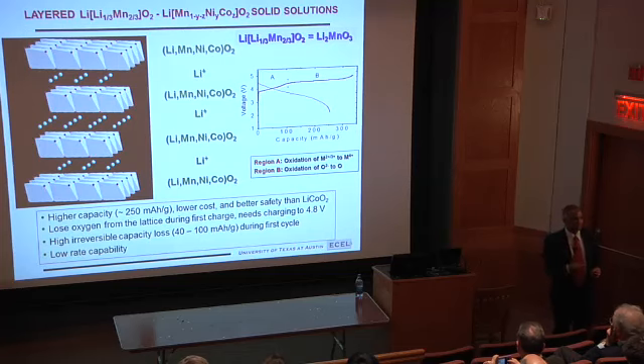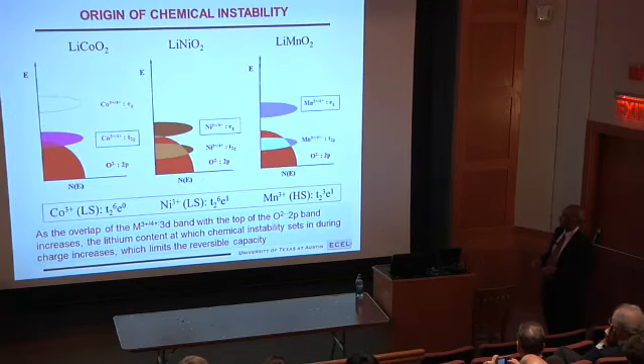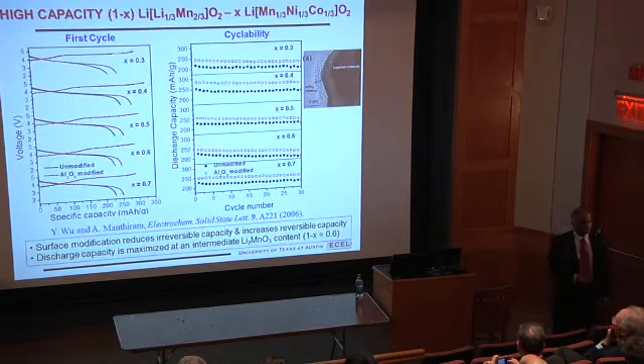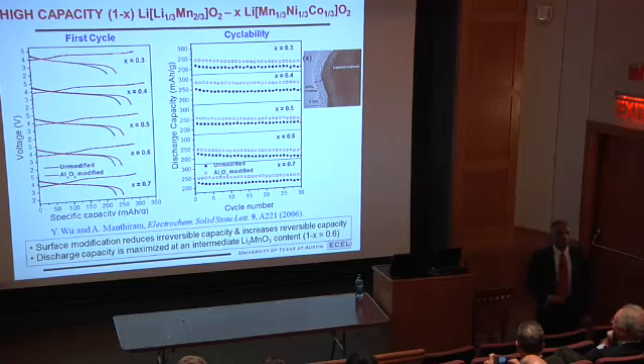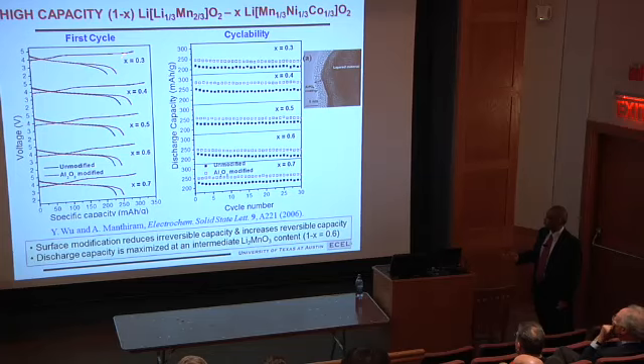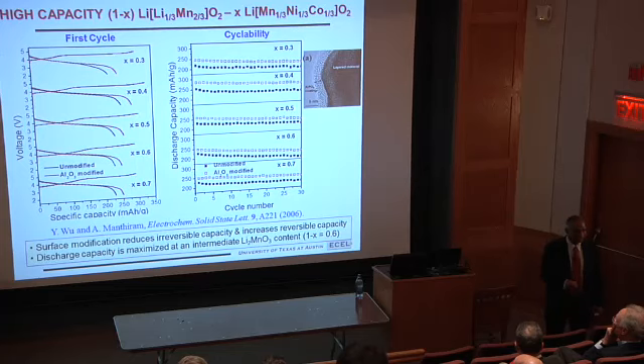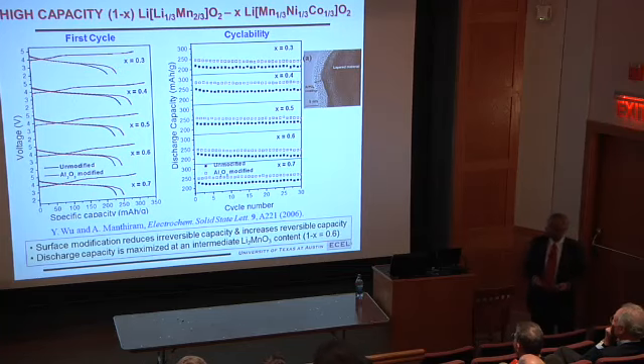It cannot be charged and discharged fast. So we have done some work. What we did is make the material, then chemically coat with aluminum oxide or aluminum phosphate. When you do that, you see the red ones are after coating, the black ones are before coating. The difference is decreased between charge and discharge. So that means we decrease the irreversible capacity loss in the first cycle, and that helps to have higher discharge capacity, as you see here. Red ones are after coating, the black ones are before coating.